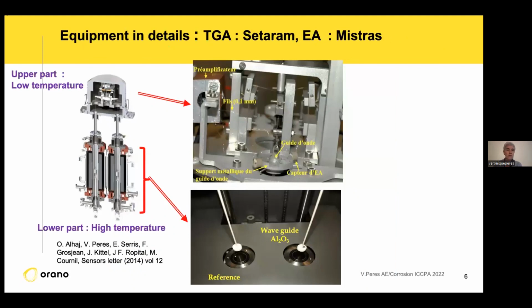I will show you some more detail of the system. You can see the upper part of the equipment, which is the Setaram one. In this part, we put some special devices. This is a sensor we put on the metallic support for the weighing, and the preamplifier is here. You can see some copper tubes, which permit us to transfer the noise from the piezoelectric system to the electric system preamplifier. At the lower part of the system, we have the high temperature, so we decided to use a waveguide in alumina. And you can see here the small sample we have in this system.